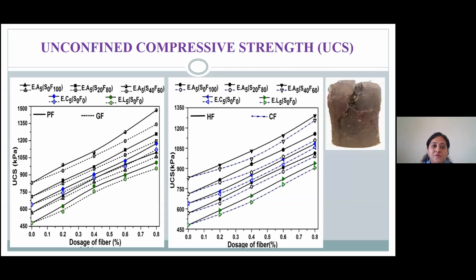We have performed the UCS, the unconfined compressive strength tests, on samples of 38/76 mm at a strain rate of around 1.25 mm per second. From the results, we can see that inclusion of alkali activated binder and fiber has significantly affected the rate of UCS, the strength gain.